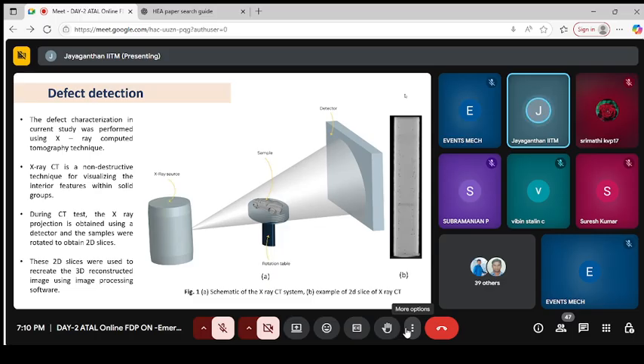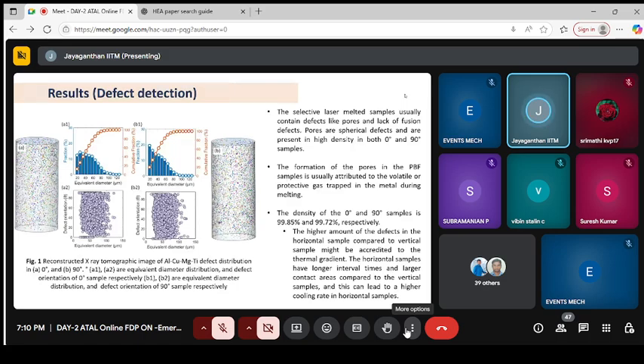Please see what the defect is, not only the presence of defects but the quantity of defects being present and how they're distributed. That also needs to be quantified for 3D printed materials. And again, going in depth, what is the density of the 3D printed part being vertically built versus horizontally built? That is given here: 99.85%, 99.72%. What we're trying to say is that with respect to different orientations, horizontally built and vertically built samples, a lot of defects are found in the horizontal sample compared to the vertical sample.